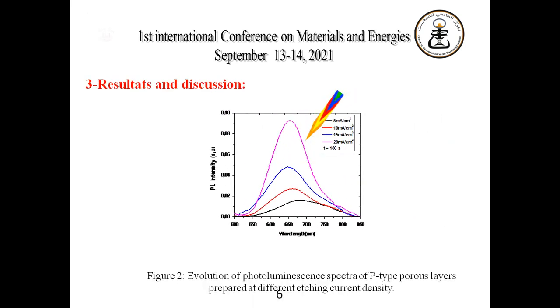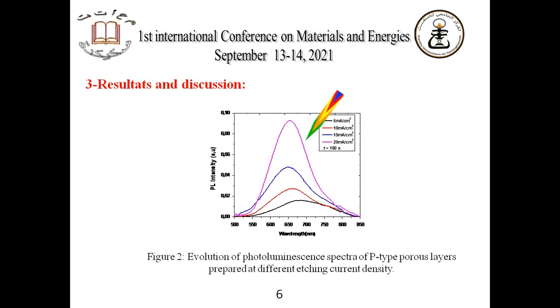In results and discussion, all the porous silicon samples showed a visible PL at room temperature. Figure 2 shows the spectra of P-type porous silicon samples that were obtained from different etching current density and etching time. The presented series in Figure 2 indicates similar variation of the PL intensities. However, a remarkable increase of the PL intensity ranged from 2.59 to 11.72 was noticed. The spectrum showed an improvement in the PL intensity as a function of etching current density.